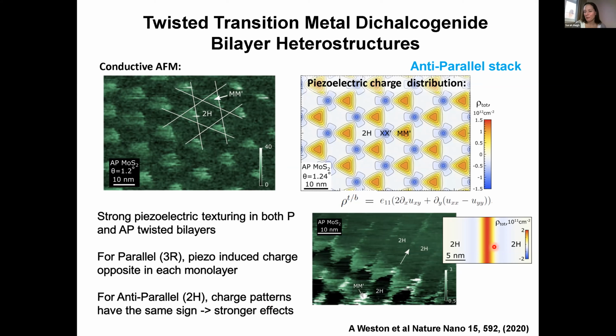And you can see that also right at the boundaries that we see for these types of materials, where we have, this is an edge and the twist has got some reconstruction happening at that edge and it's constrained, so we've not got that full Kagome lattice, we've just got this 2H type of dislocation running along there.